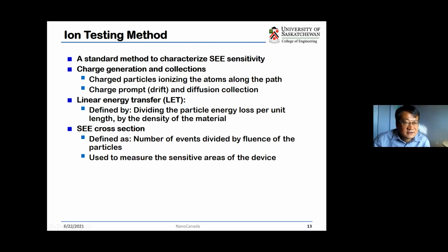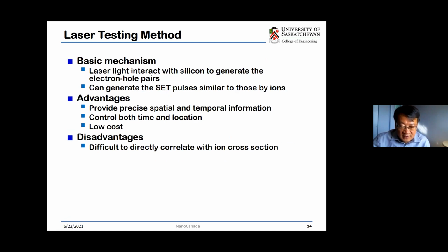However, the problem with ion testing is that, for example, in Canada, we only have TRIUMF that has the accelerated proton, and we don't have a heavy ion facility. So this accelerated particle facility is not easy to access and is quite expensive. So in this field, we came up with another approach. We use laser. Basically, the mechanism is that the laser light can interact with silicon to generate electron hole pairs, right? And they can generate SET pulses similar to those produced by ions. So we can use this pulsed laser to mimic the ion hit, and then we study the single event. The advantage is that we can provide precise spatial and temporal information, right? Because we can control the location and timing. And it's a very good debugging tool.